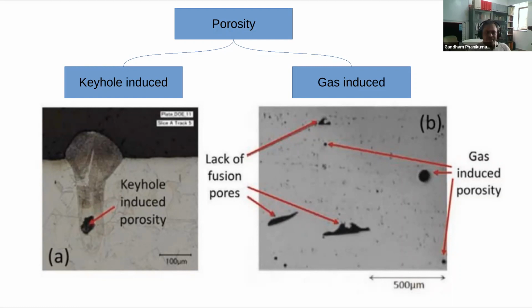So the keyhole idea, I have actually described the concept of keyhole formation in high energy beams in my NPTEL lecture on YouTube. So if you search for NPTEL lectures with my name, you will see one of those. I have explained the keyhole formation, the vapor formation, etc. Now here I would just briefly tell you that when a very high power laser is incident on a metallic material, and if the temperature is increased to the extent that a small amount of vapor is formed, then that vapor will absorb the laser heat completely. Suddenly the efficiency of absorption will go from 10-15% to 100%, and therefore the laser will penetrate much deeper, and it will form a vapor column.